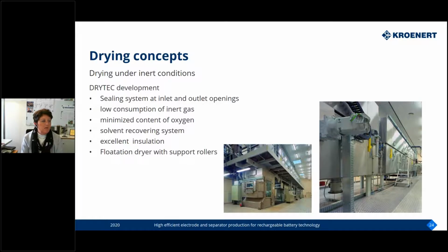And the second advantage is when you have an inert clean dryer, you can go much higher with the solvent concentration in the air of the dryer, and with that you can much better control the drying process, because you can play in the first drying zones with a certain kind of overloading of solvents, and with that you can avoid that the solvents are evaporating too fast, and with that the film formation during the drying process is much better. We can handle flotation dryer, we can handle support-driven roller dryer.